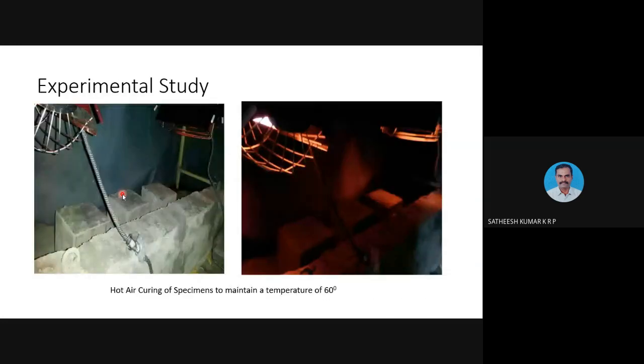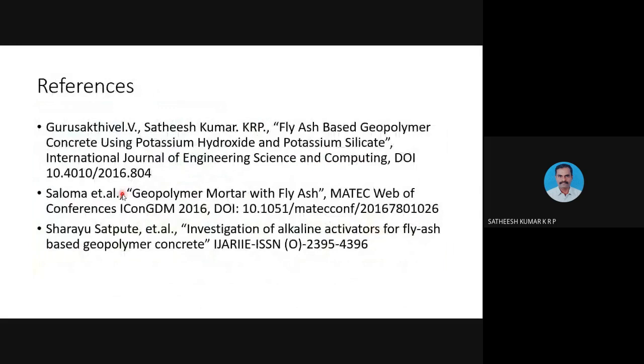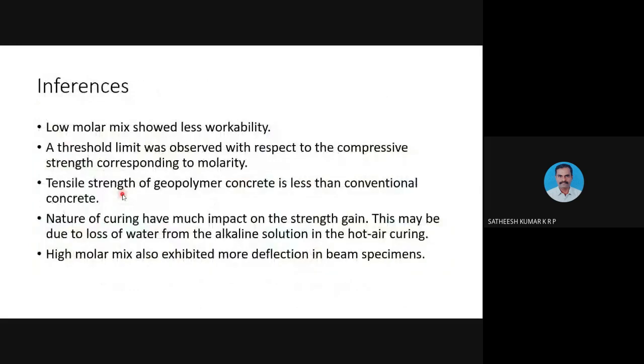I have not given the mix here. As I said, the mix is like we can say the fly ash to fine aggregate to coarse aggregate is 1:1.75:4. So the very high value of the coarse aggregates might be the reason for the low slump values.